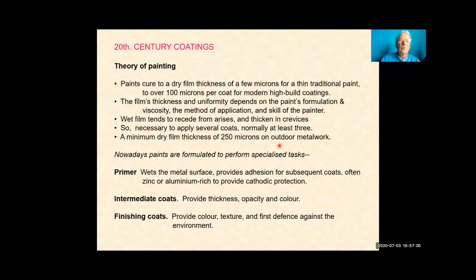Nowadays, the paints are formulated to do each job rather well. So a primer is designed, and it has material in it to make it wet the metal surface, to stick really well, and often to provide cathodic protection. So you may well find powdered zinc or aluminium in it to provide that protection. The intermediate coat simply builds it up, and they can get 100, 125 micron of paint on in one go, one coating, to provide the opacity and the color. And then the finish coat provides the first defense against the environment, as we say. So it gives the color, texture, and nowadays we're very fond of high gloss paint.